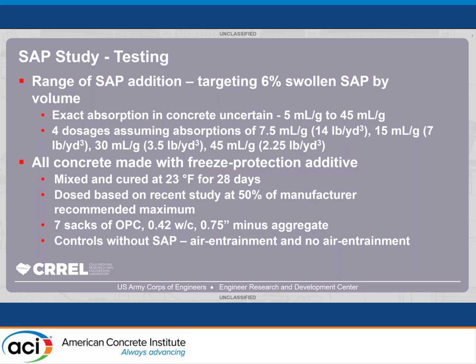And then the concrete mix was pretty standard. It was a 7-sack Portland cement mix with a 0.42 water to cement ratio and a 3/4 nominal aggregate size. So in addition to those 4 dosages that we made, we had 2 controls, and so 6 mixtures total. And those 2 controls were one that had your typical chemical air entrainment, and then a mixture that had no air entrainment at all.